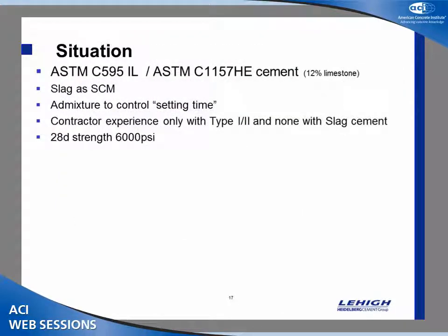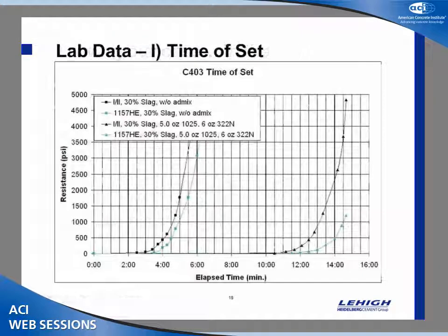But we still had to do a lot of testing. This is a huge slip form project, and so strength is really the secondary consideration. What you have to do is design your mix so it slip forms. In other words, the concrete has to be able to sustain itself, and you have this huge slip form working its way up. Once you start this, it doesn't stop. The process goes on. So we did a lot of testing, and one of the reasons for the pushback was the different set times of the limestone, and at the time we were using a 1157 HE, high early cement. The pushback was that it's going to be much too fast setting. And we said, that's why we're going to balance that with the use of the slag.